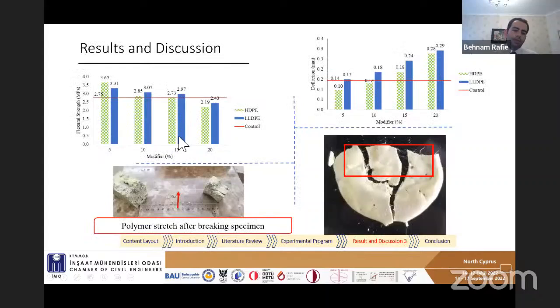In flexural strengths and deflection, adding 5 and 10% increased the flexural strengths. However, adding 15 and 20% of modifiers make our specimens more ductile. So as you see, the polymers here act like fiber inside the sulfur. And here you can see after flexural test, you can see the stretch of the polymer inside the sample. So this is a good result to increase the flexibility of the sample and specimens.